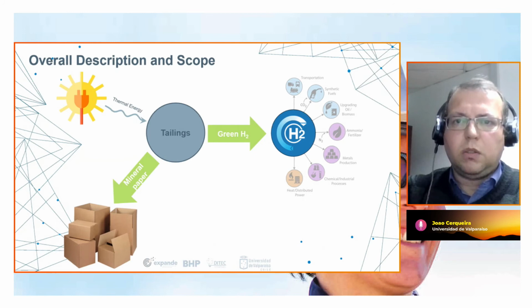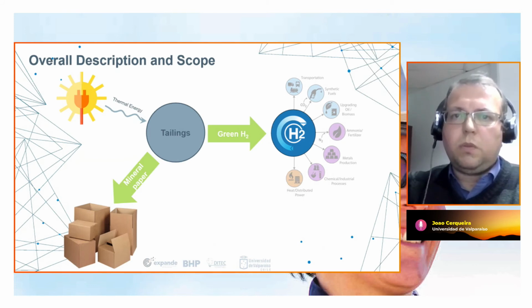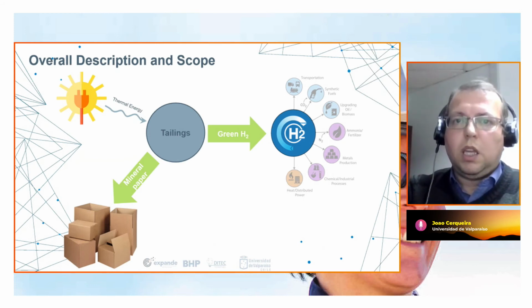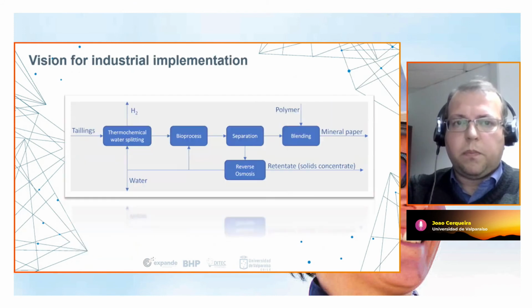On the other hand, in relation to mineral paper, the potential market corresponds to 21 million tons per year in Latin America, or between 44 and 59 million tons per year worldwide, if we consider only 30% of its market. Considering all the above, the resulting industrial proposal corresponds to the main process scheme presented here, where tailings are firstly treated to produce green hydrogen by thermochemical water splitting. Afterwards, the remaining minerals will be processed in order to solubilize the anionic metals, after which the insoluble fraction will be separated and processed into mineral paper with some polymer addition, and the liquid fraction will be pH neutralized and go through reverse osmosis.